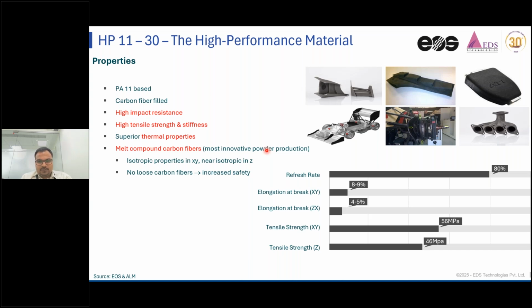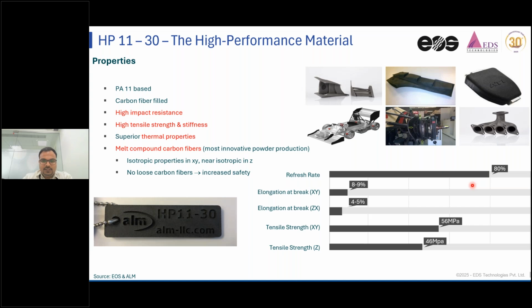When we print the actual part, you can see the mechanical strength here. In the XY, these parts are at 56 MPa, and in Z they are 46 MPa. And these materials are highly reusable again. 80% of the material can be reused.